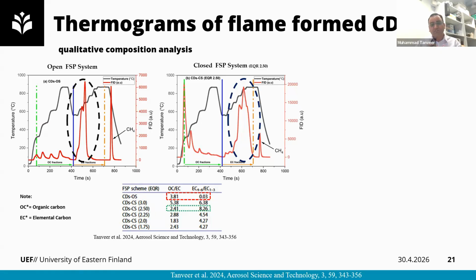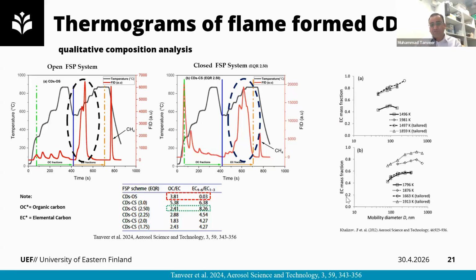This shows that we have a higher amount of elemental carbon in our closed system. Because elemental carbon is a thermally more stable and graphitized form of carbon, this shows that our nanostructures produced through closed flame pyrolysis are more graphitic in nature. And this can also be seen from this finding that temperature can increase the graphitization of the sample by increasing the EC value.